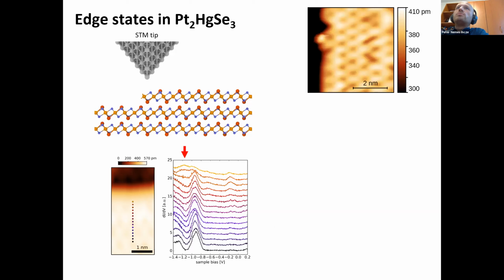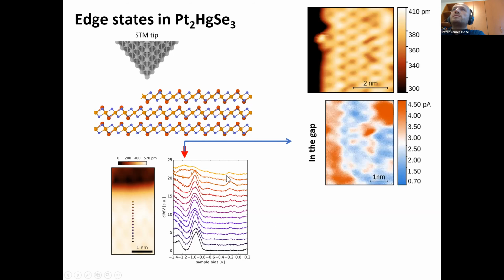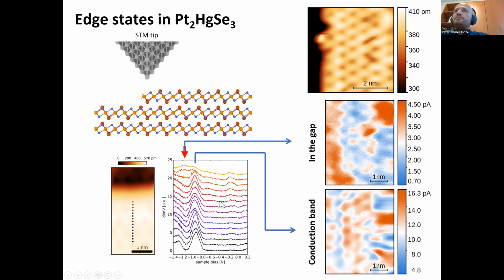Now, if you just go to this energy, to this voltage, and do a mapping of this whole step edge, you can measure this local density of states as a function of position quite well, and you can see that just at the edge you have an increase in the tunneling conductance, which is again indicative of an increased density of states within the band gap. If you do a similar experiment, but now in the conduction band, you can see that there is basically nothing at this edge, and the tunneling conductivity is just modulated by the atomic lattice, and not much else happens.